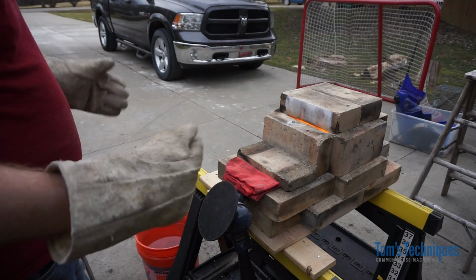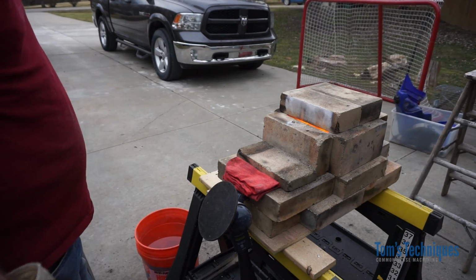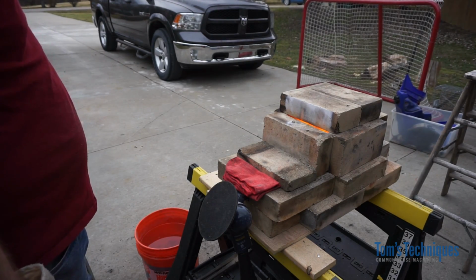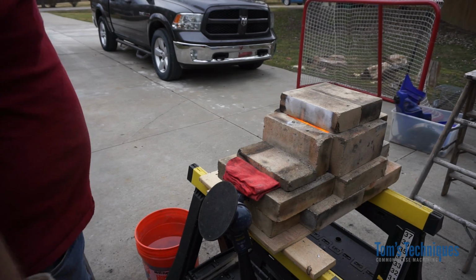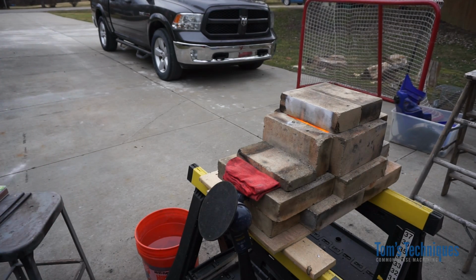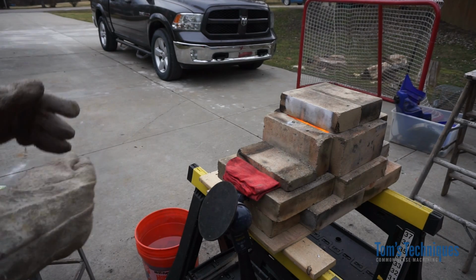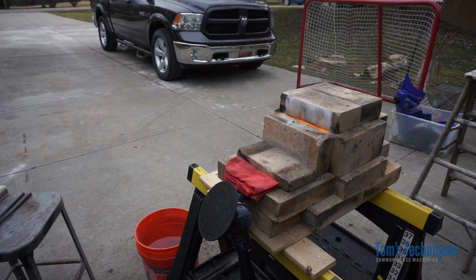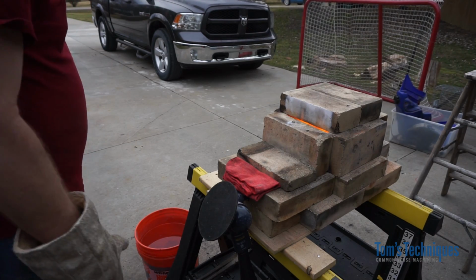In fact, I was looking up some of the temperatures. If you keep it at about 1600 degrees for 4 hours, you get a 60 thousandths deep case. That's a lot of hard metal on the outside of a part. We don't need that much. 10-15 thousandths is plenty, and that's what we'll end up with on here.